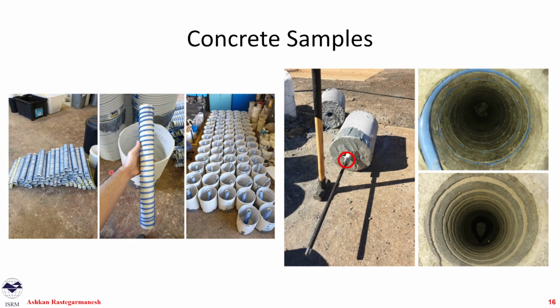For our concrete samples, we had column formworks, which were 300 mm in diameter. We cut them 450 length, and we had these PVC pipes, which were our boreholes. The diameter of them was based on the manufacturer recommended diameter of annulus for each cable. And we put cables around them, like wires, to have sort of rifling. We do that to make sure that our failure only happens on the cable-grout or resin interface, not between the grout or resin and rock interface.